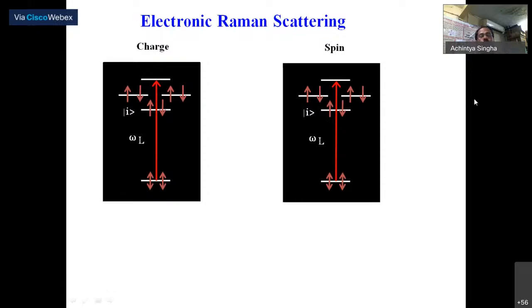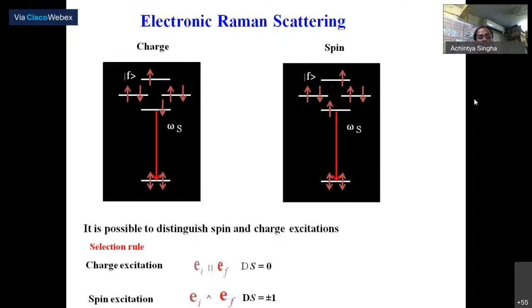So you can measure the charge and spin excitation of a material using Raman spectroscopy. If you look carefully, you can see how the excitation occurs. In the charge excitation, there will be no change of spin, and for spin excitation, you will get a change of spin. Charge excitation has delta S equal to 0, and spin excitation has delta S equal to plus or minus 1.